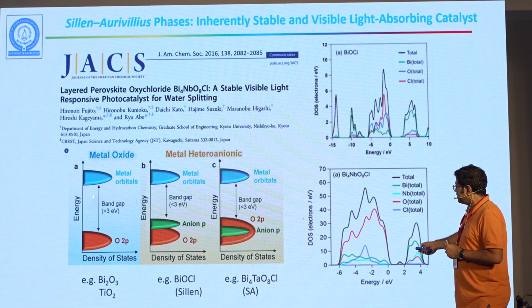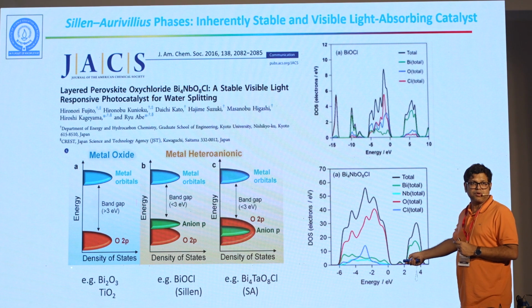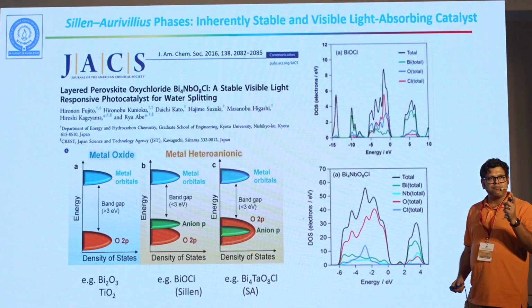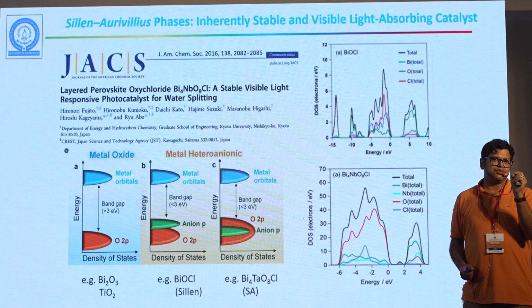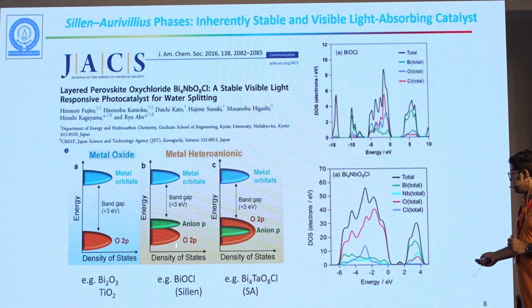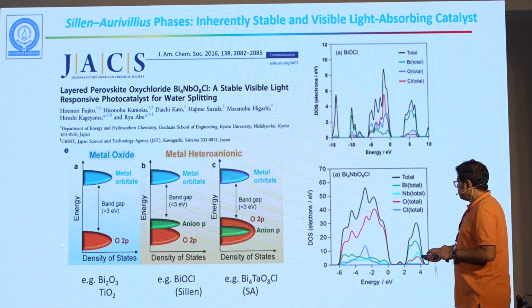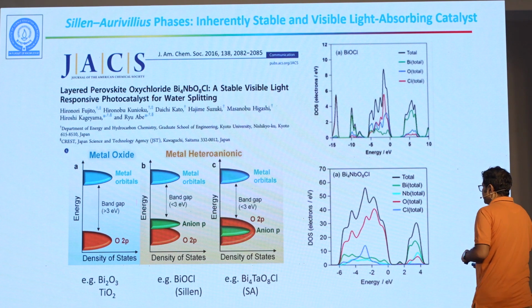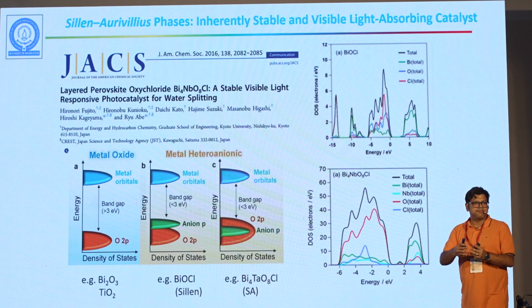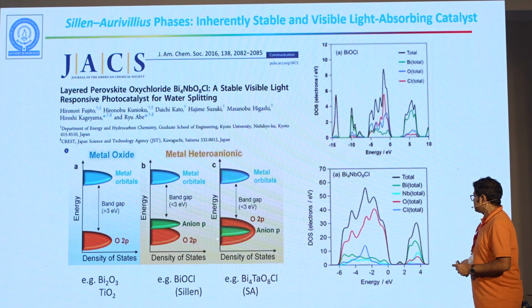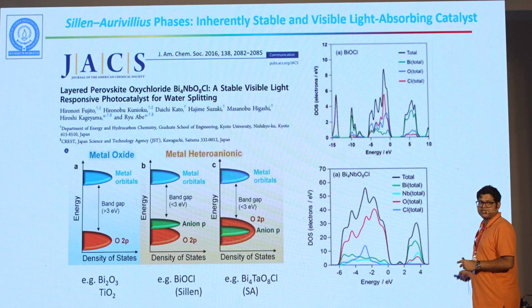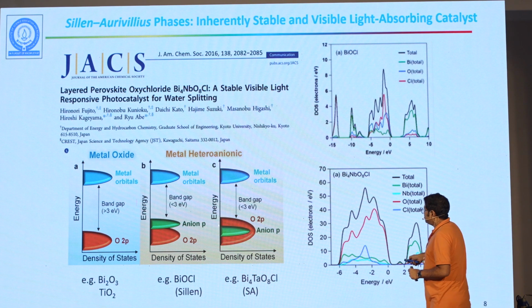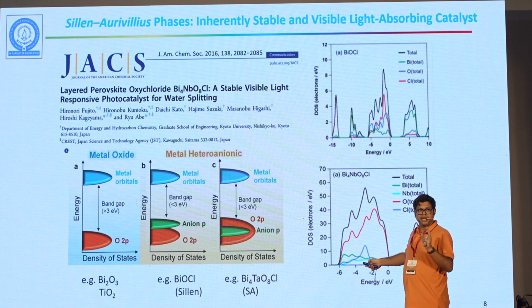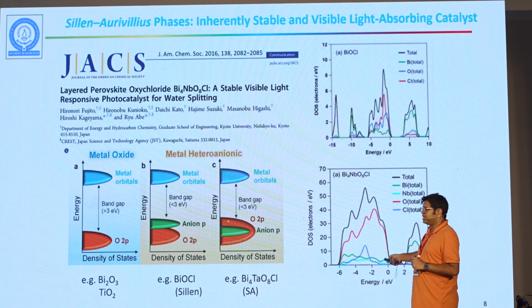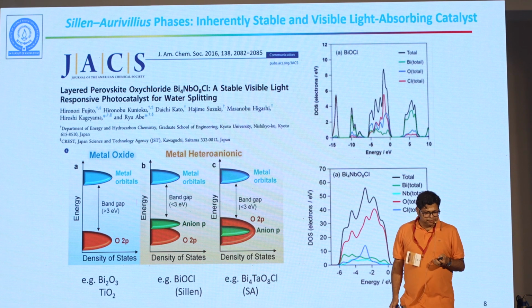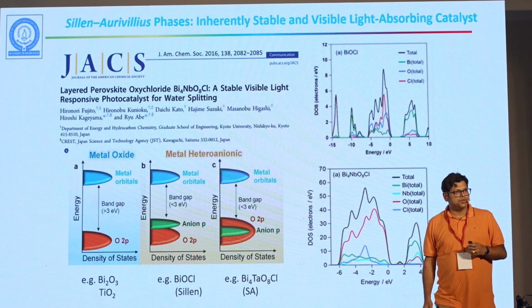Now if you look at metal oxides, the valence band is made of oxygen, not of chlorine. So these are stable. But the problem with oxides is that they are normally white. They do not absorb sunlight. BiOCl absorbs sunlight, but it is not stable. But when you mix them together, because of the changes in crystal structure, what happens is that these oxygen p bands get flattened out, or say they expand. So this is the schematic. These are some theoretical results. But essentially what it means is that now we have a structure where the band gap is very similar to BiOCl or the Sillen phases, but the valence band consists of oxygen, and therefore it is stable. Therefore, this was used for water splitting with very high efficiencies.